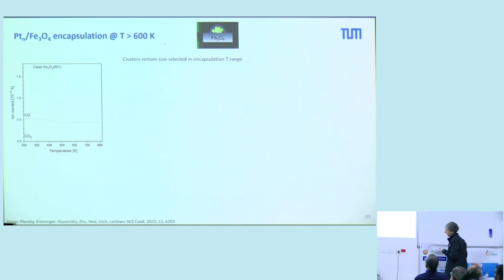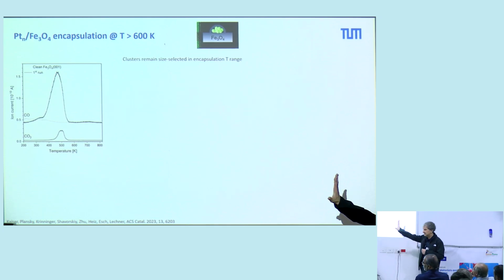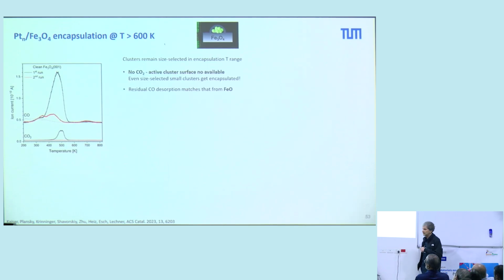Then we go higher in temperature. Here you see a clean iron oxide surface. We have very little CO adsorption, no CO2 oxidation. We then again deposit these clusters on the surface. This is the result I showed you with the CO desorption, CO2 formation. But if you now heat up to 800 K, go down, and again dose CO, you have a different behavior. You see here now CO desorbing in this broad feature, and this is typical for iron oxide. And most important, you don't see any CO2. That means we speculate now that the cluster is covered with iron oxide.